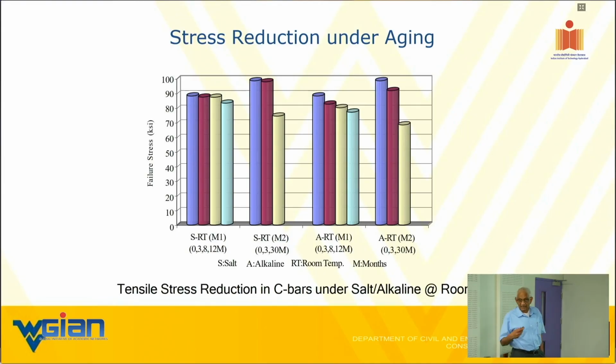So that again is all in line with what happens under alkali silica reactions and what have you. No matter what, the alkali silica reactions have influence, and salt has less effect than alkalis. Both have effect, but one is slightly less effect, less damage.